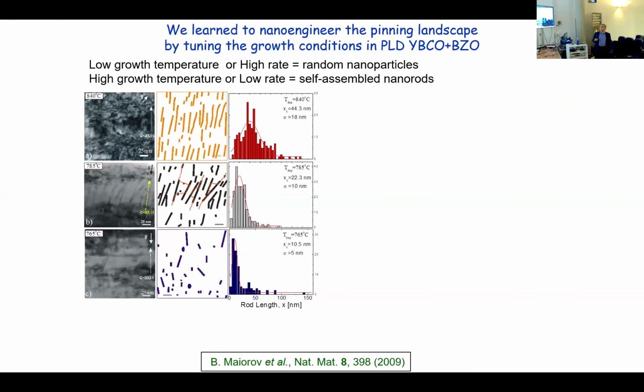We learn, and I will not go into detail on this, but we learn to tune the growing conditions. We learned that if we deposited the films at very high temperatures, we had essentially long and aligned nanorods. If we go to very low temperatures, kinetically, the system didn't have time to form nanorods, so they had mostly randomly distributed nanoparticles. And at some intermediate temperatures, you have splayed nanorods with some distribution of angles and some nanoparticles.